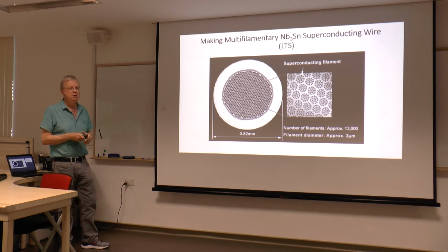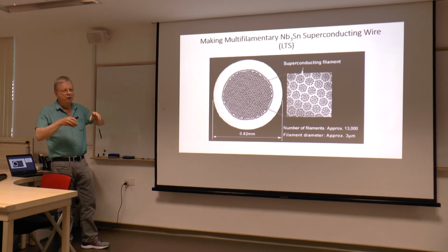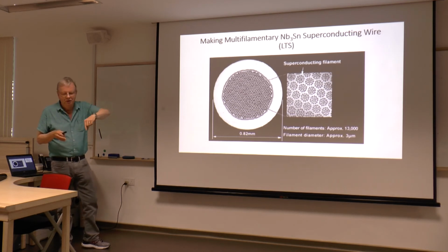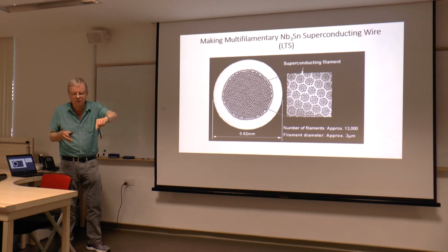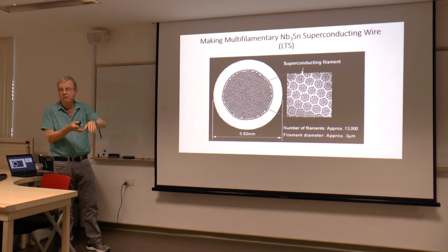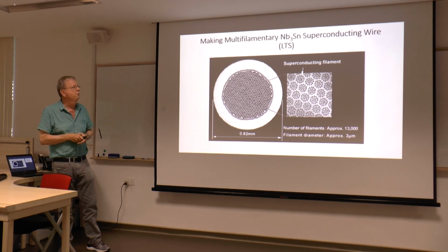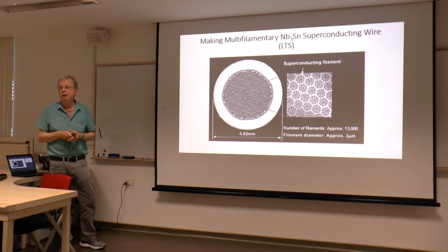But in the copper is the tin part of the bronze. And so what you do is you draw the wire down, and you actually wrap it on the mandrel so it's in its curved form, because if you wrap niobium-3 tin in too short of a radius, it'll crack the A15 brittle structure as well. You wrap it on the magnet, and then you anneal it in an oven. And the tin and the niobium react. The tin comes out of the bronze, the niobium sits there, and if you do a good job, most of the cross-section of the niobium wire will turn into niobium-3 tin.